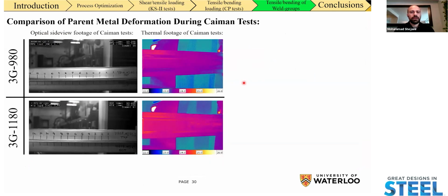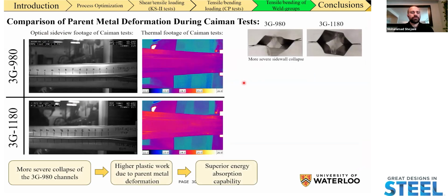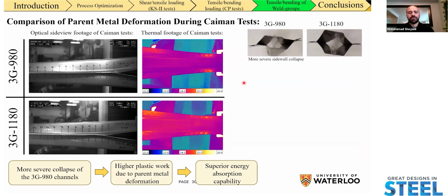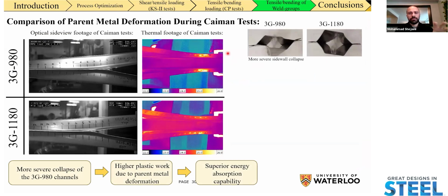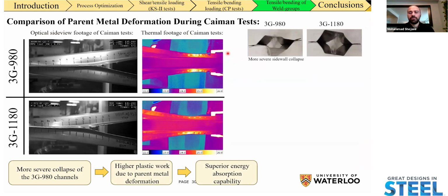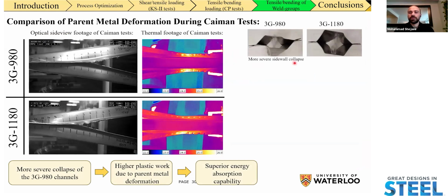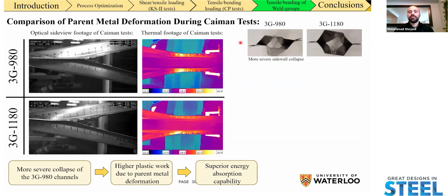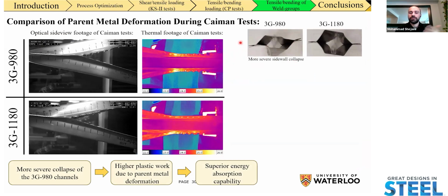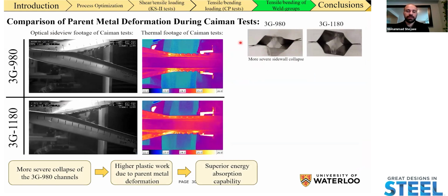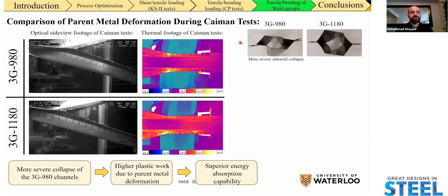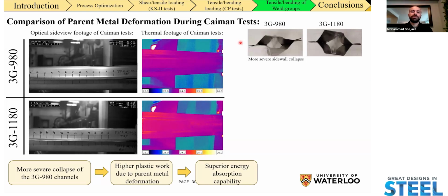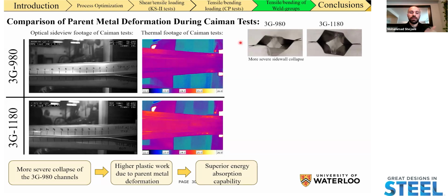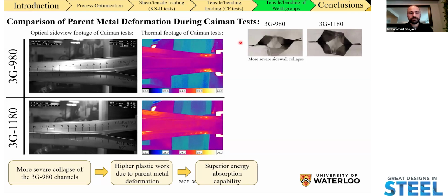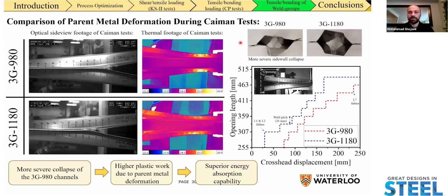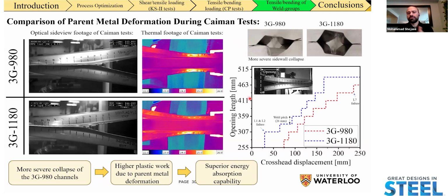Once we look at the data from the optical camera and also the thermal camera, we can see sequential failures happening on both sides, but by the end of the test, we have a more severe collapse of the sidewalls in the 3G 980 material. And this sidewall channel collapse is definitely contributing to the energy absorption capability difference between the two materials. So one of the reasons that we have superior mechanical performance from the 3G 980 is definitely going to be this more ductile flange that we have in the Cayman component test.